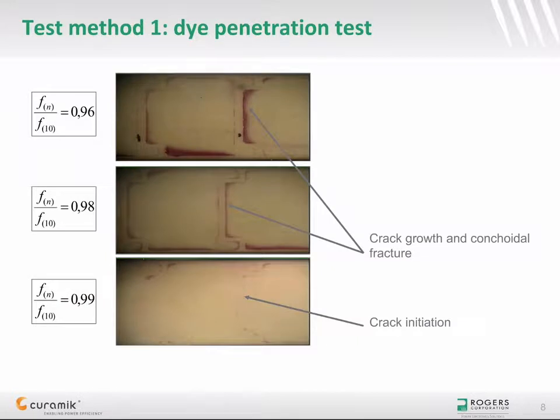Let's take a look now at the test methods and criteria that are typically used to assess the lifetime of substrates. The first method is to remove the samples from the climatic chambers after a given number of temperature cycles, etch copper away, and look for any cracks in the ceramic. For this purpose, a dye penetrant inspection is applied. This is a low-cost inspection method used to locate surface breaking defects in all non-porous materials like ceramics.